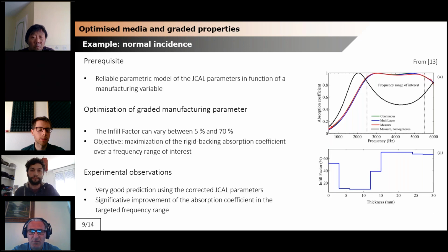So now let's speak about one example. This one is in normal incidence. What we want to do is optimize the gradient of properties through the thickness of the material. The property here is still the infill factor of the microlattice, in order to have a perfect absorption in a targeted frequency range. So we start with the homogeneous material, which has this black absorption curve, and we say that we want in this frequency range to have the highest absorption coefficient possible.